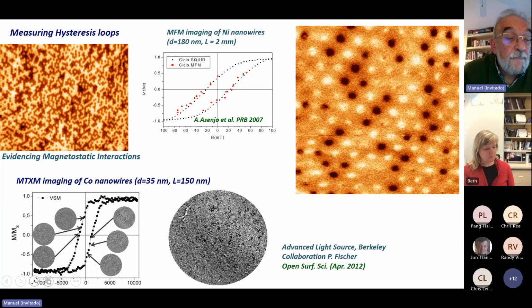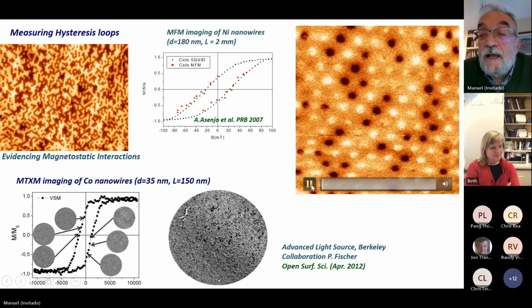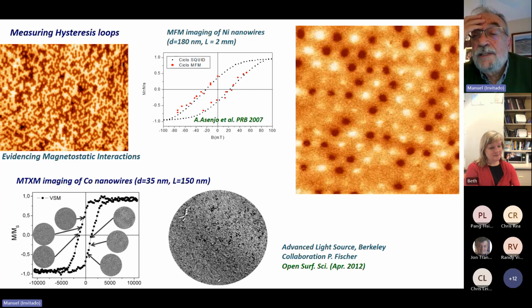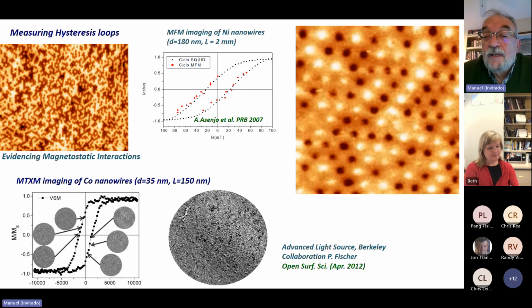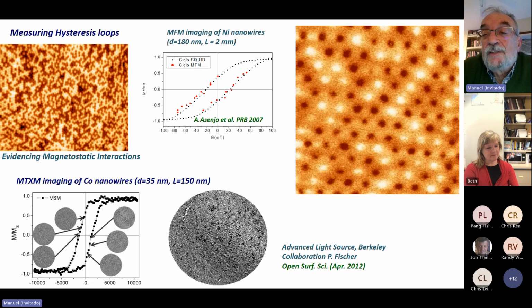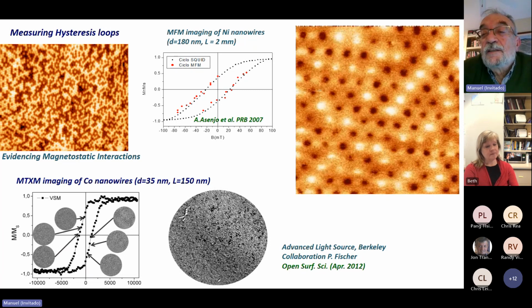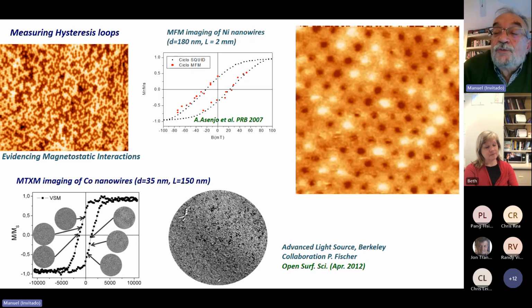So I have another video. Oh, sorry. Let me try to show you. I hope you can see that when we apply a magnetic field parallel to the wires, some of the white points become black, indicating that the wires reverse magnetization individually, until the applied field, in that case, was not large enough to reach saturation. But, okay, go back to the laser. So you see the red points correspond to the hysteresis loop obtained through the magnetic force microscopy imaging. In fact, at each point, the magnetization can be determined just by counting how many black and white points we have.